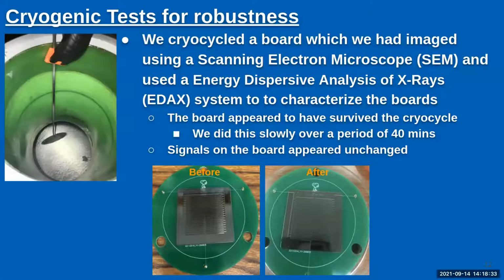So we took those boards and cryocycled one of these boards, then followed that cryocycling with a scanning electron microscope using an energy dispersive analysis of X-rays to characterize what occurred to this board having undergone a cryocycle. First and foremost, the board appeared to have survived a cryocycle. We did this cryocycle rather slowly, lowering the board all the way into liquid argon and then bringing it up over a period of 40 minutes. After retesting the board in the same vacuum apparatus, the signals appeared to be unchanged.